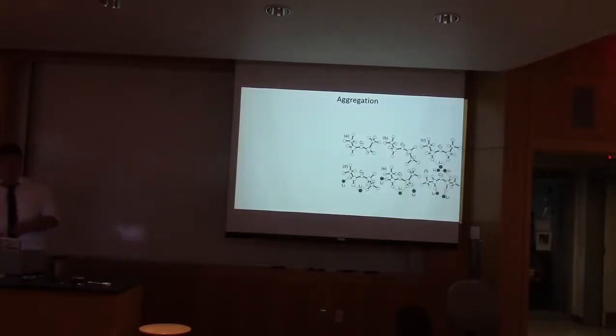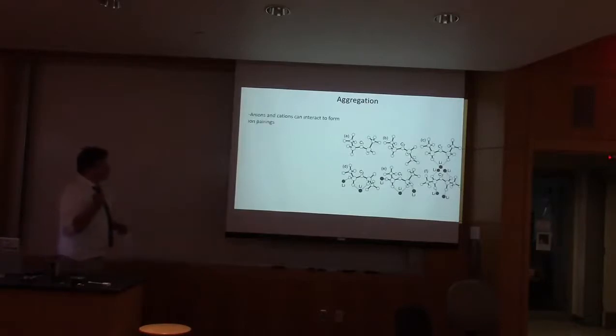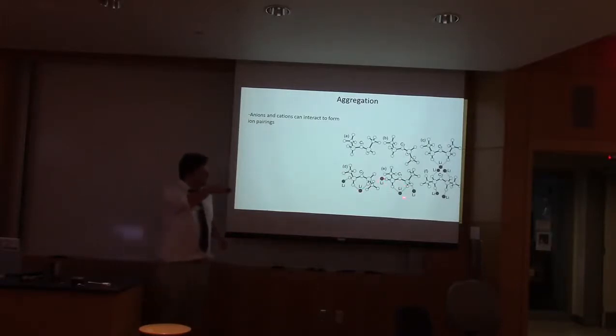This gets us into the topic of aggregation. Aggregation, in its most simple, is really the strong interactions between the anions and cations in a liquid. In the case specifically of our lithium ion, we can imagine that lithium cations can bond, or not bond physically, but very strongly intermolecularly interact with our associated anion here. And they can interact in a number of different ways, as you can see in this particular diagram.